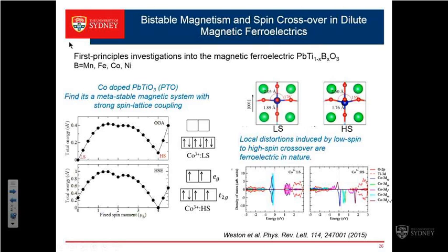You can see that the barrier height is actually larger with a more accurate approach. Okay, here it's 0.4, here it's 1. But you can see that the qualitative behavior is the same. You have this barrier here between two different spin states, low spin and high spin. So what does that mean? It means that this system is capable of being switched possibly by an external electric field.